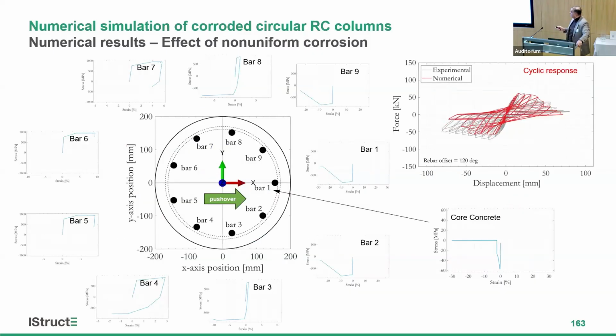And then we looked at it. So we had essentially 27 different material models across all these three sections. And as I said, when you have non-uniform corrosion, we start rotating the bars around the section. So this is 9 bars. Imagine we rotate them. You see, this is the stress state of the bars at the final stage. And you get this response. So it's quite important to be able to identify this localized corrosion and how it behaves. Otherwise, depending on the loading direction, we get a different capacity. So that's another reason why localized corrosion is very important.